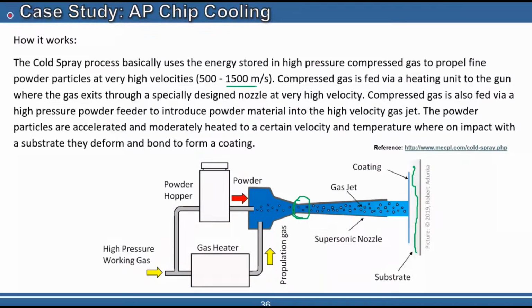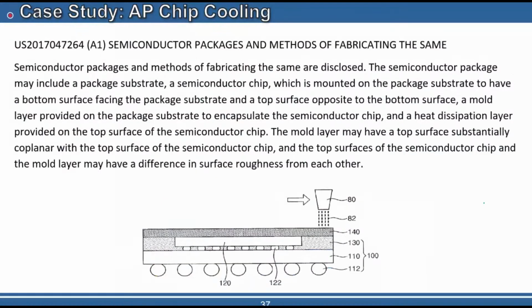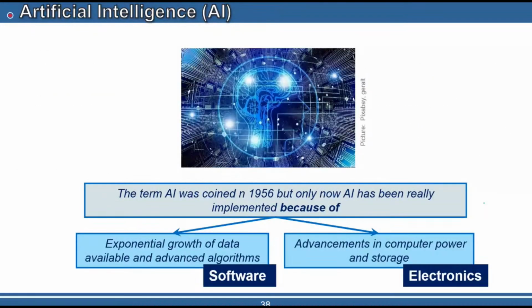Can you imagine? This is a huge speed of particles, which means each particle has a very high kinetic energy. When the particle hits the surface, this kinetic energy transforms to a thermal energy. Okay, this is a local melting. Size of particles is really small, it is 40 micron. So the area where the particle is molten is very small. No overheating for the substrate. So we propose the same technology for fabricating of semiconductor chip, AP chip, and cooling this chip with the layer.